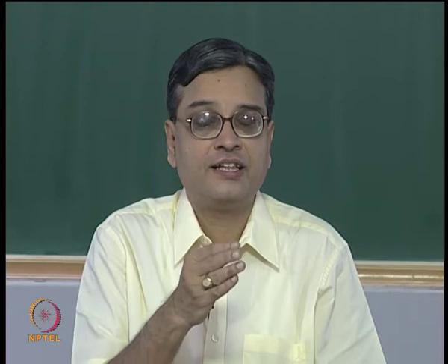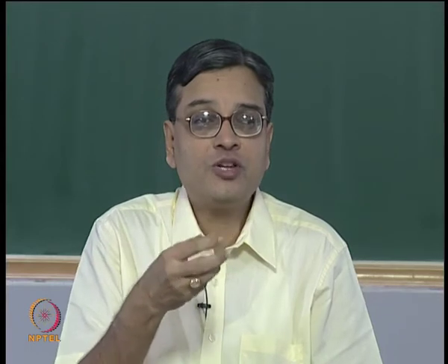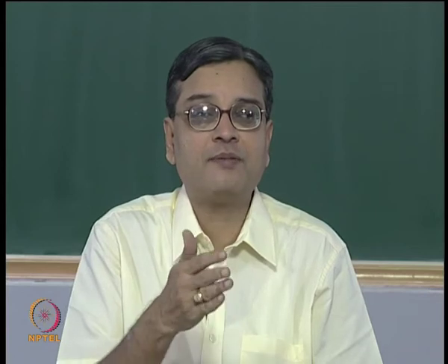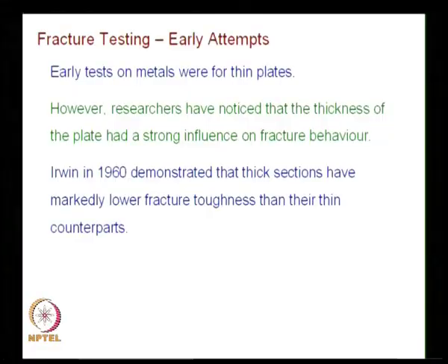But if you look at the early stages, they arrived at this result based on experience, and intuitively they try to propose why this happens. When you say something is a material property, it should behave like a material property. What they found was it behaves like a material property only when plane strain conditions were satisfied.